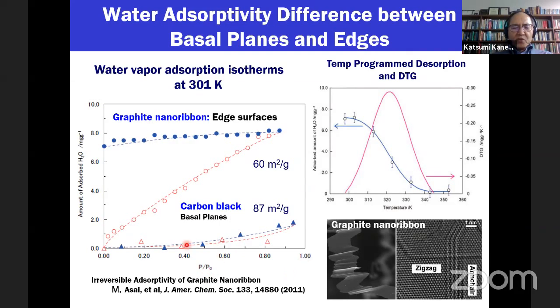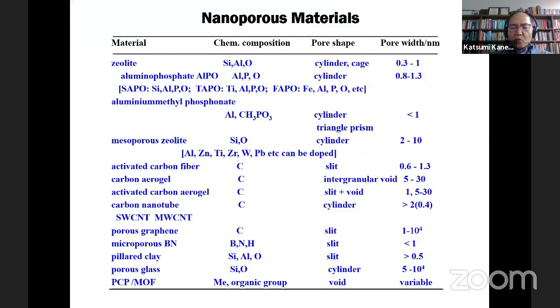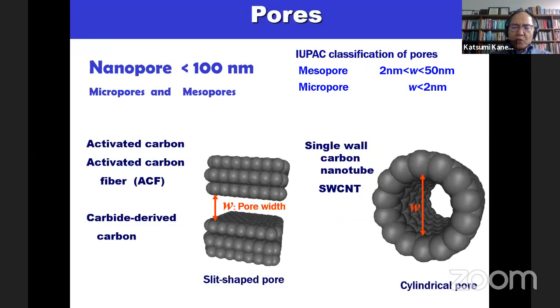Here I will show you the water adsorption isotherm of the carbon black, non-oxidized carbon black. And this is the graphite nanoribbon. The surface area is not so greatly different, but the carbon black cannot adsorb the water vapor so much. But the graphite nanoribbons gradually adsorb, and the adsorbed water is not desorbed. So they should be half chemisorbed. So this is a very special case. But in the ordinary case, the carbon interacts very weakly.